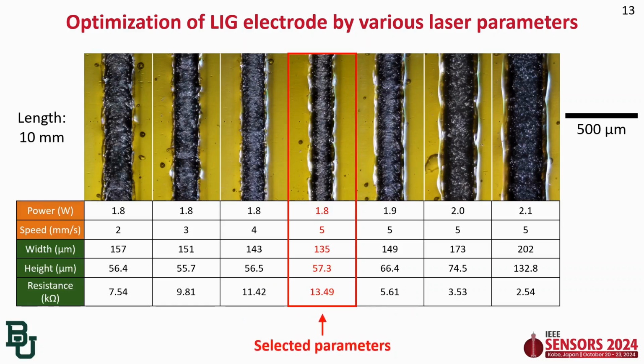We studied various laser parameters to find an optimal processing condition for maximum sensitivity. The optical images show 10 mm LIG lines under various processing conditions of the laser. We measured the resistance of LIG lines with different width and height by changing the power and velocity of the laser. It was found that the resistance increases with increased velocity and decreases with increased power. We selected the power of 1.8 watt and speed of 5 mm per second, showing the highest resistance of the LIG line, and these parameters were used to fabricate the dense array serpentine LIG electrode.